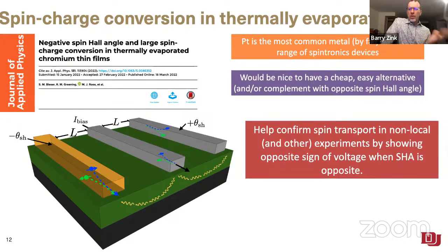Okay, so we've been interested in understanding this sort of spin flow in what's called a non-local spin geometry. I'm not going to talk about this in great detail today, but just by way of the history of how we started looking at chromium. What we really wanted to do was to have an easily produced spin Hall material that would have the negative spin Hall angle compared to platinum, so that we could help understand what's really spin and what's coming from a bunch of other basically charge-driven effects in these sorts of experiments, and help understand that by putting both those spin detectors on the exact same chunk of material, excite them with the same original spin current, and then see the magnon flow have opposite signs on the two different detectors. This was sort of my dream of how we could try to do this and to kind of simplify or clarify the results that we were getting out.